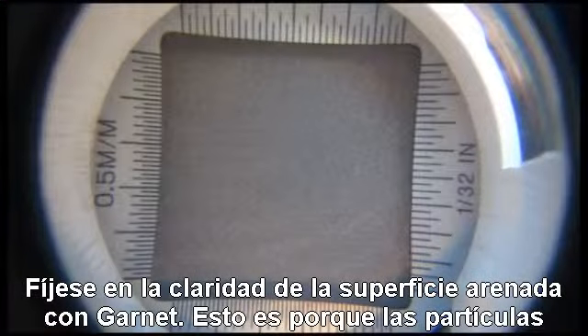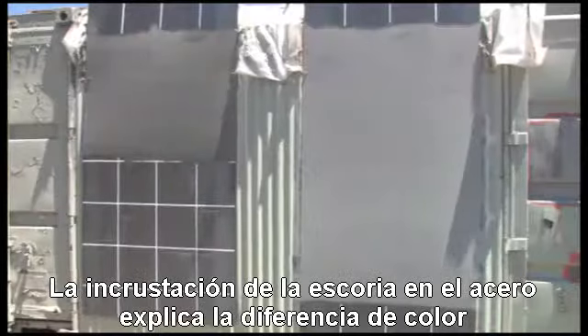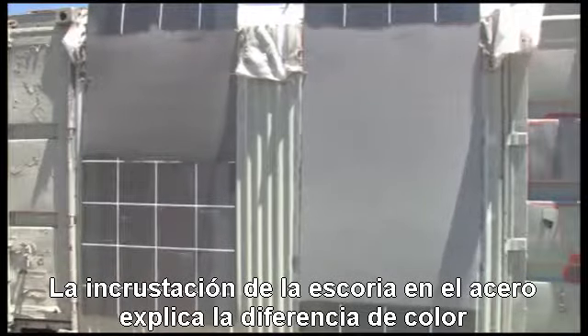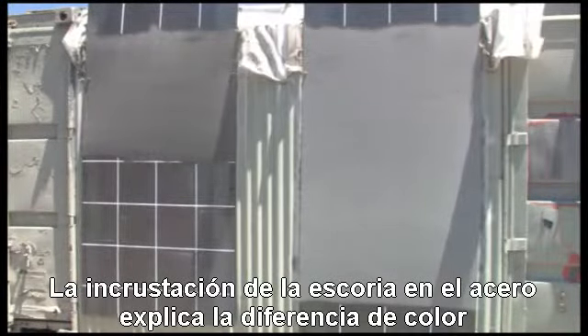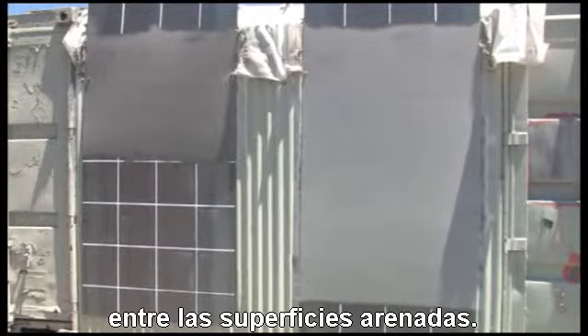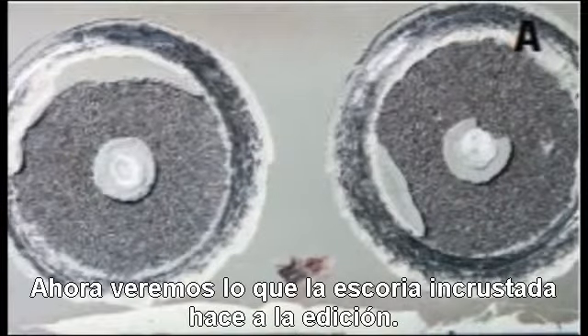Note the cleanliness of the garnet blasted surface. This is because the garnet particles bounce off the steel instead of impregnating the surface like slag. The impregnation of the slag into the steel now explains the stark color difference between the blasted surfaces. Now we look at what the impregnated slag does to adhesion.